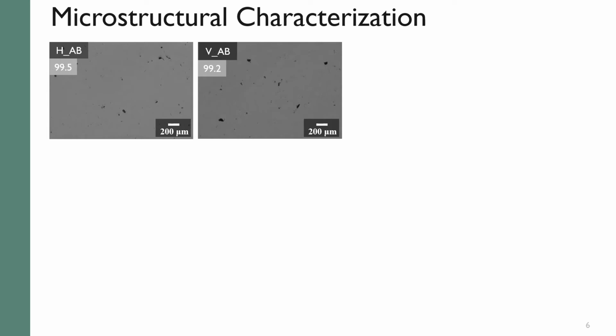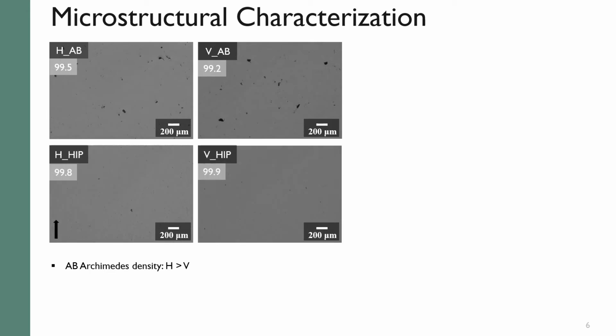Here you can see the optical microscopy images of horizontal and vertical as-built samples for the microstructural characterization. And the values are representing the average Archimedes density values, showing slightly higher density was achieved for horizontal samples as compared to vertical samples. And here you can see the optical microscopy images for horizontal and vertical HIP samples presenting increased density for the HIP condition.